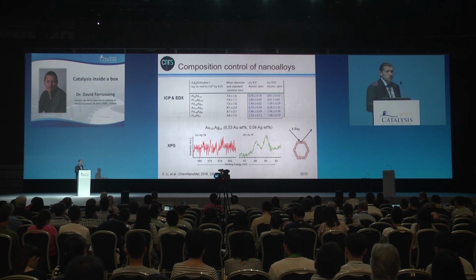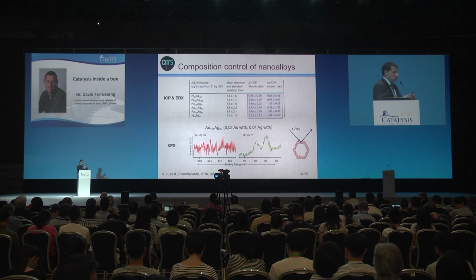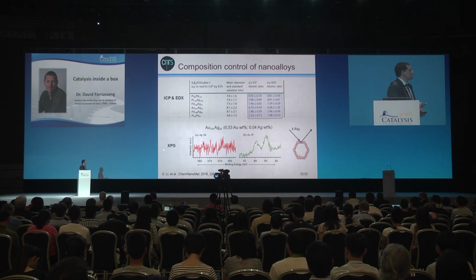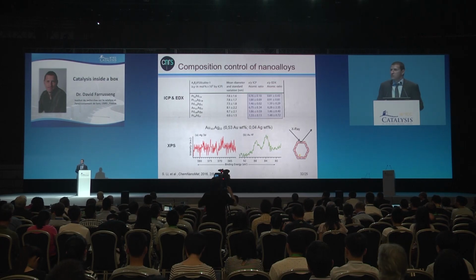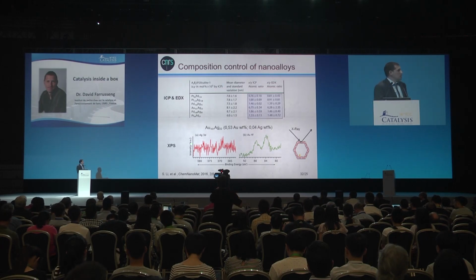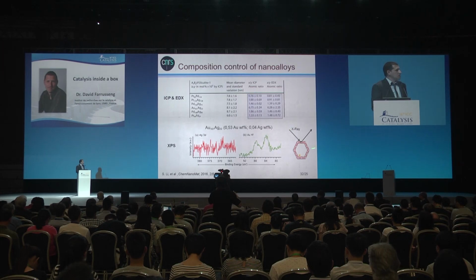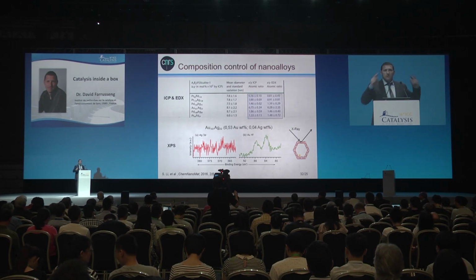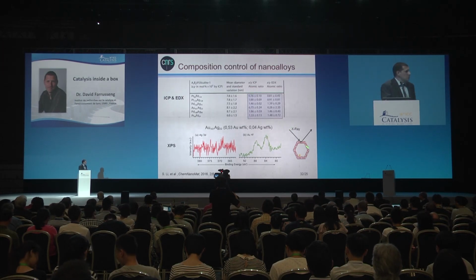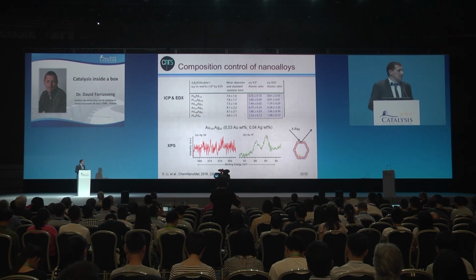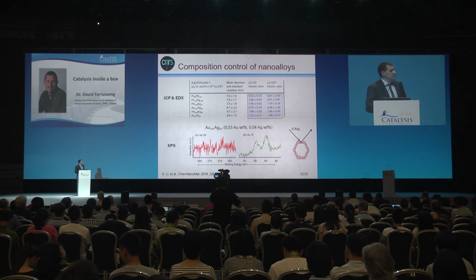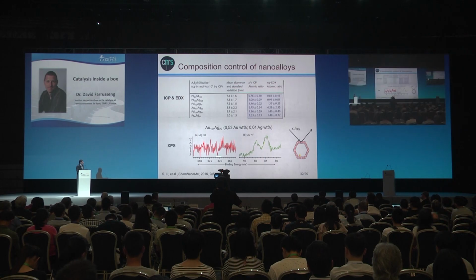We wanted to go one step further and look at the surface composition. It is known that XPS is the most appropriate technique to look at the surface. But here we cannot do that because the signal is shielded by the zeolite membranes. The XPS cannot cross the zeolite membranes. So in conclusion, it tells you that all the particles are well encapsulated in the zeolite membrane.